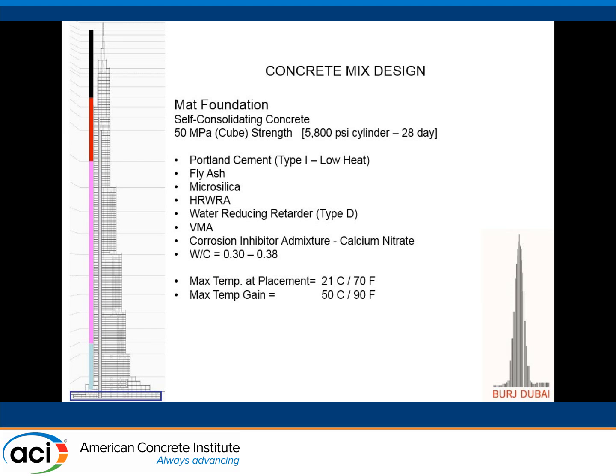Moving on to the mat foundation. Mat foundation, we did use self-consolidating concrete, similar to Trump Tower. We had about 6,000 psi cylinder strength at 28 days. Portland cement fly ash mix with microsilica once again, and you see the water-reducing admixture in combination with a viscosity modifier for the self-consolidating characteristic.